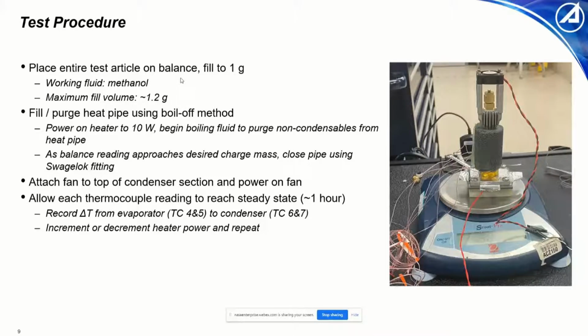All of our test results were measured at 3 input power levels: 5, 10, and 15 watts. I say increment or decrement because heating versus cooling, in terms of our boiling behavior in the evaporator section, we noticed became very, very important. I'll discuss that later, but in some cases we started at 10 watts and then went down to 5. In others we were at 10 and went up to 15. But in every case we somehow captured 5, 10, and 15 watts on at least heating, if not cooling as well.